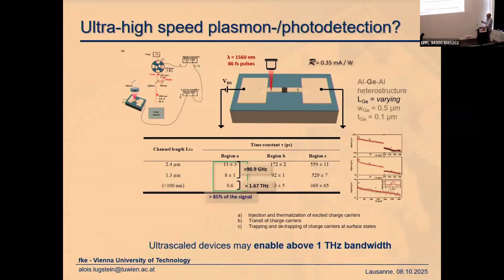Then we have a region which is directly correlated to the length of the segment. This is the transfer time. So the plasmons are propagating here along this waveguide, then they decay to the hot charge carriers, which is a very fast process. Then they have to traverse through the device, which is region B, and finally region C, which has a very long time constant. This is related to traps in the devices, so they're not well passivated. We have a lot of traps, particularly on the devices which were based on germanium.